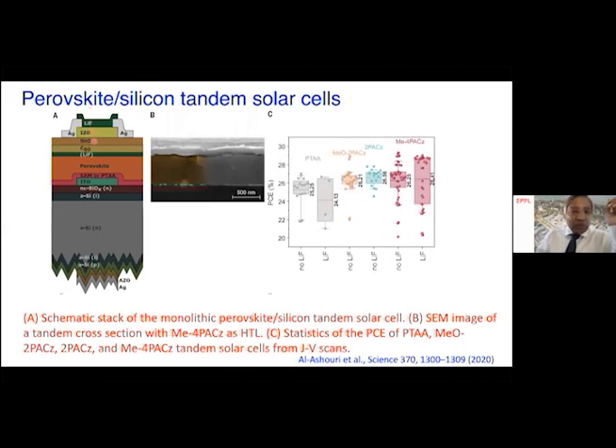When you shine the light from the top, most of the visible light is absorbed by the perovskite layer up to 800 nanometers. Now it creates positive and negative charges. Positive charges go to the ITO side, and the negative charges go to the electron transporting layer. So the positive charges coming from the perovskite and the negative charges coming from the silicon wafer, they recombine here. And now what you collect is electrons from the top cell and positive charges from the bottom cell. And if they are current matching, then you can add the VOC of the two cells, which can be 1.8, 1.75. So here are the different hole transporting materials.